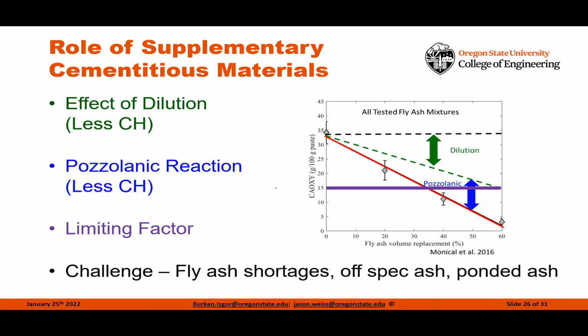Now, what we're able to do is design these mixtures to account for the fact that we can actually dilute the system by replacing a portion of the cement with something else. So maybe it's limestone. We can actually get to this dilution line. But if we also have something that reacts pozzolanically, we can take this further and we can now predict the amount of calcium hydroxide and the amount of calcium oxychloride that's going to exist inside of that mixture.